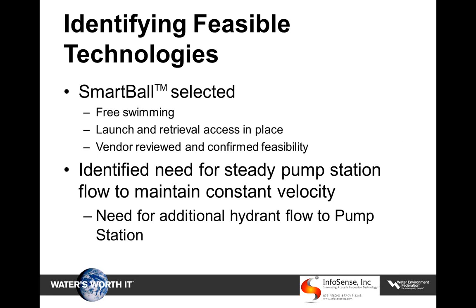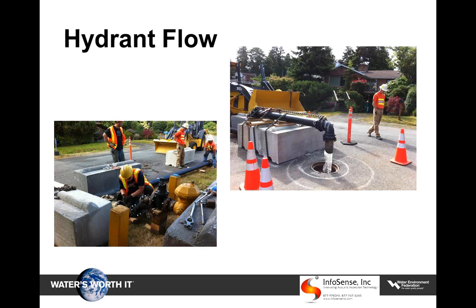And that all seemed pretty well until I told them that we needed about 1,000 GPM for about 2.5 hours. And we ended up finding a hydrant that happened to be a fairly high-pressure hydrant also, about 160 PSI. And with the help of an on-call contractor and our construction crews, and once again our colleagues at SPU, we were able to successfully deliver for a fairly long time. We ended up running about 3 hours of hydrant flow to be able to get the pump station up to a flow rate that would deliver the Smart Ball from one end to the other.